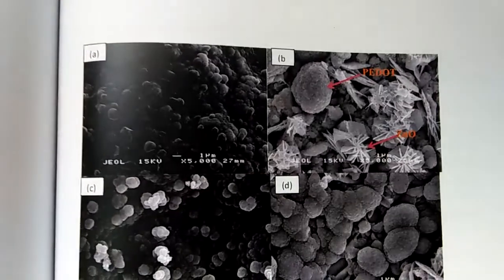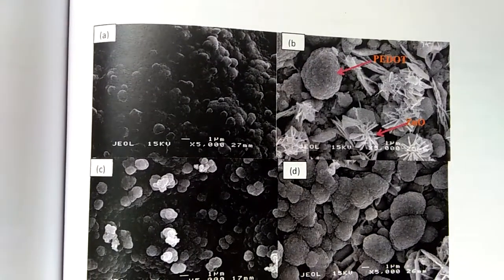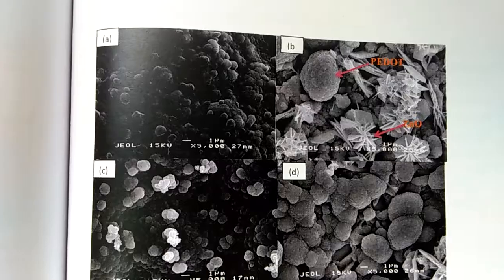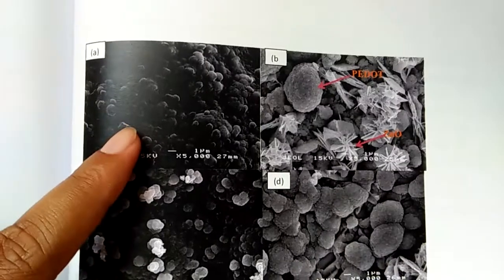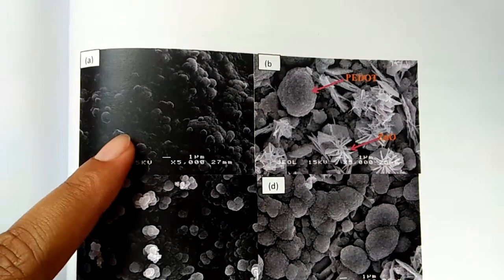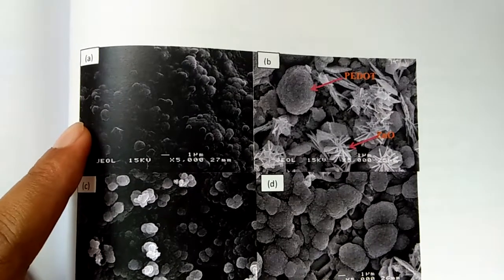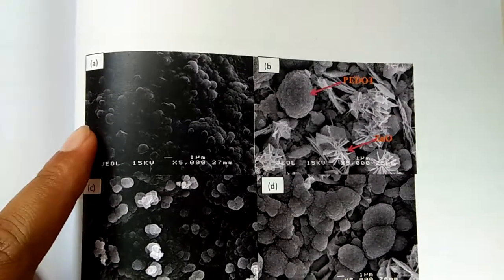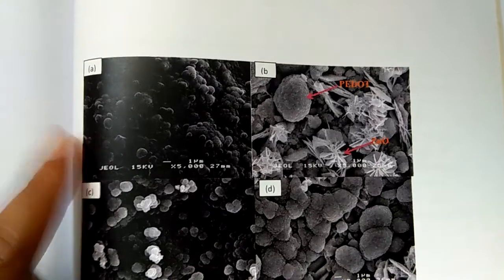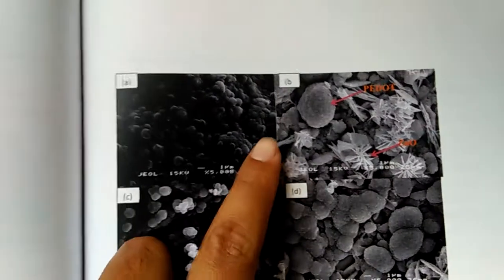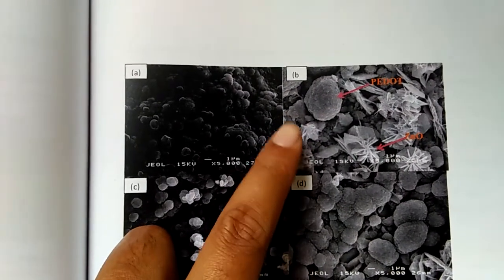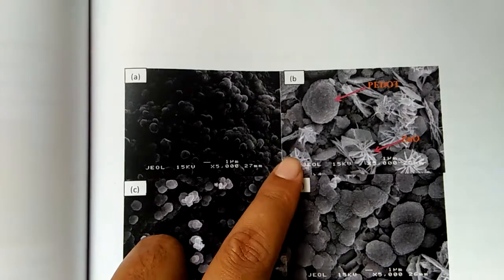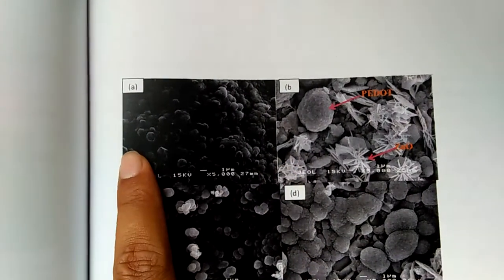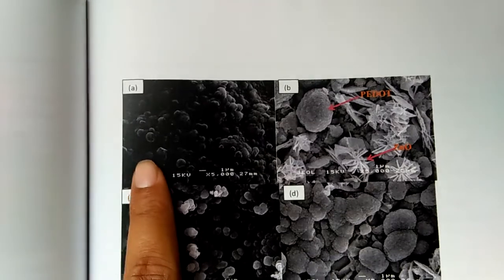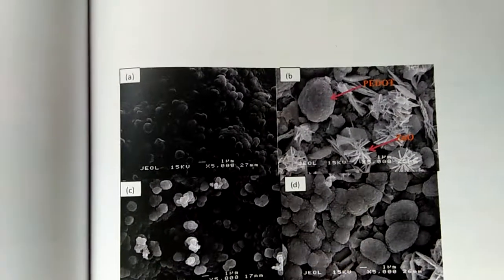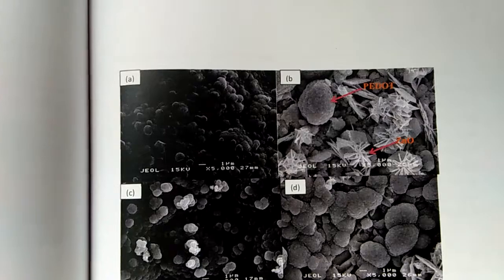It's very simple, yet it might be crucial. If you deposit PEDOT first, it might not work because PEDOT cannot sustain a high temperature. When you put it inside a water bath, PEDOT will peel off. So you must deposit zinc oxide first, and then you dry it, and then you deposit PEDOT. Then you get the composite PEDOT zinc oxide. So it's very simple. You can try it and play around with the parameters.